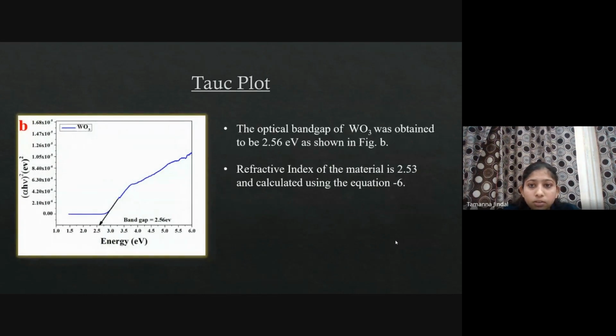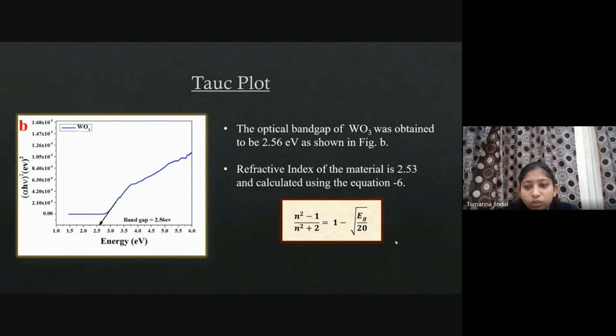Tauc plot: here, the optical band gap of WO3 was obtained using this method, which is found to be 2.56 electron volt as shown in the figure, and the refractive index was found to be 2.53, which used the equation given below.